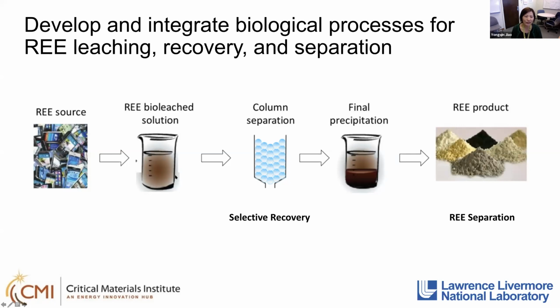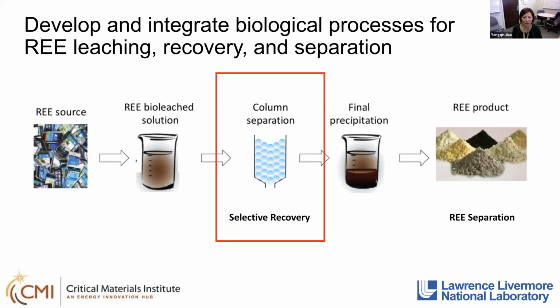And then once the metals are in solution, we apply a column separation approach for selective recovery and separation of the rare earths from the rest of the non-rare earth metals. Then we could subject this solution to precipitation to form total rare earth oxides, followed by a rare earth separation step to produce individual rare earth elements. For today, I'm going to first focus on the column separation for selective recovery, and later touch upon rare earth separation a little bit.